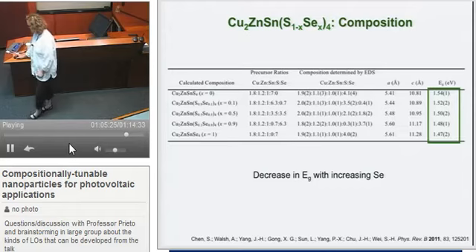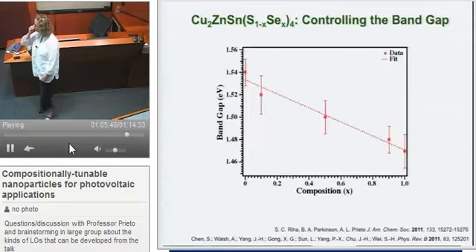And this part, I still don't really understand. Papers have come out since we published this where they do show a 1 eV band gap for copper, zinc, tin, and selenium. So I'm not sure. I think this might have something to do with the way the band gaps are calculated from the UV-vis spectra. So we have a lot more thinking to do in terms of this. But the trend at least matches theory. And we did put error bars on that.